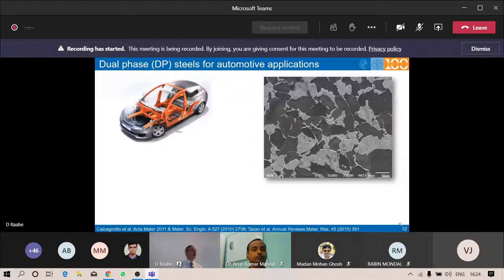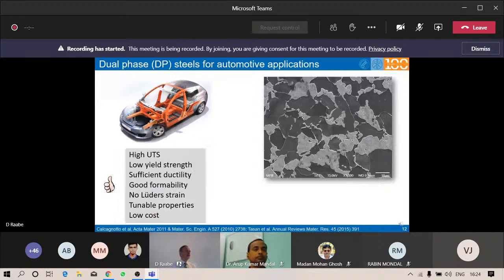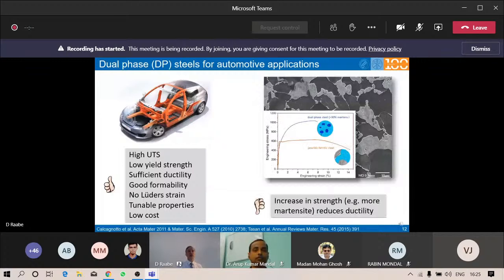They have a high ultimate tensile strength, UTS, low yield strength, which is good for forming operations, but they have sufficient ductility, good formability, no Lüder strain, that is very important for engineering parts, and they have highly tunable properties and, of course, very, very low costs. Now, the tuning comes, for instance, through measures like grain size reduction or martensite volume fraction increase or carbon content increase. And we all know that would come also at the cost of ductility.